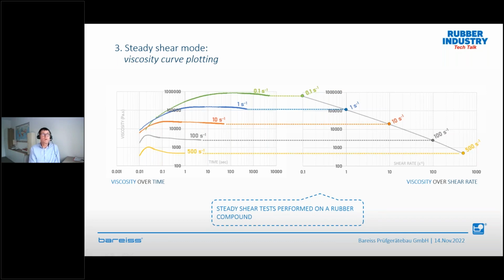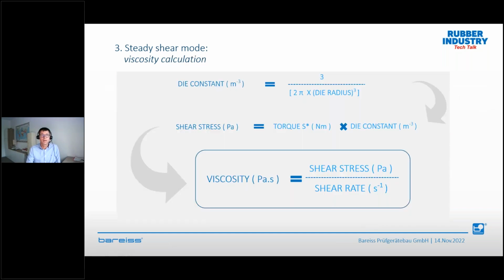viscosity curves. So now we have no longer a dynamic viscosity. Dynamic viscosity is always oscillating, but in your machine outside, it's never oscillating, it's rotating everything. Yeah. So this is coming much closer to reality than what we measured before, or what is done on a frequency sweep.